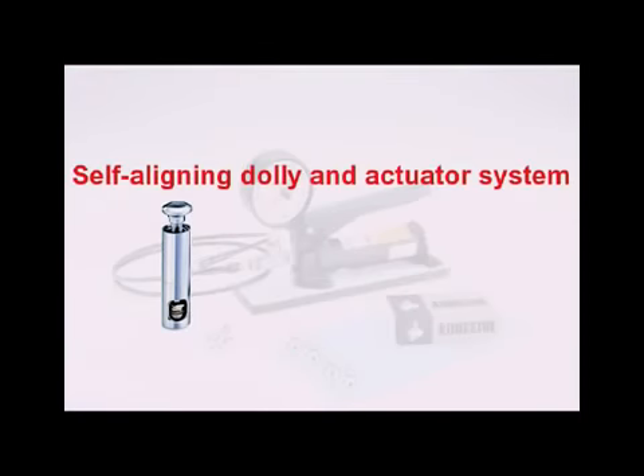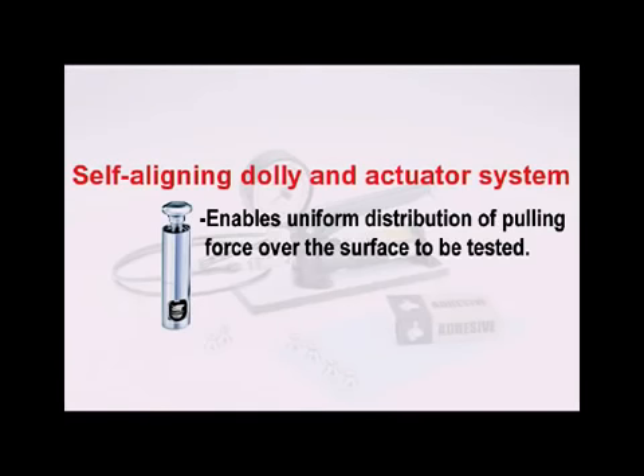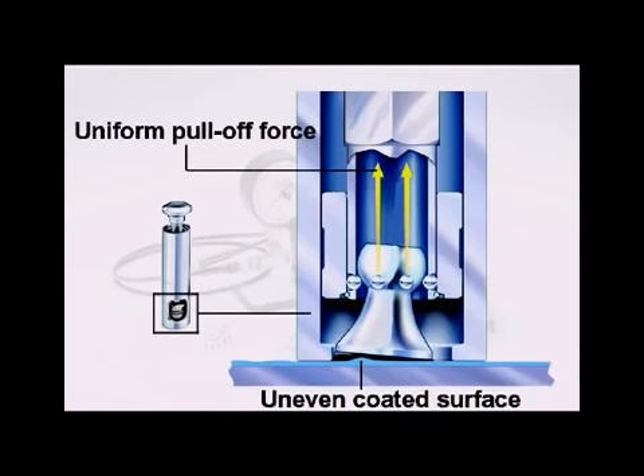The Positest self-aligning dolly and actuator system enables uniform distribution of the pulling force over the surface being tested. It maximizes repeatability by eliminating the possibility of shear forces, which may result in one-sided pull-offs on rough and uneven surfaces. Pull-offs are always perpendicular to the substrate.